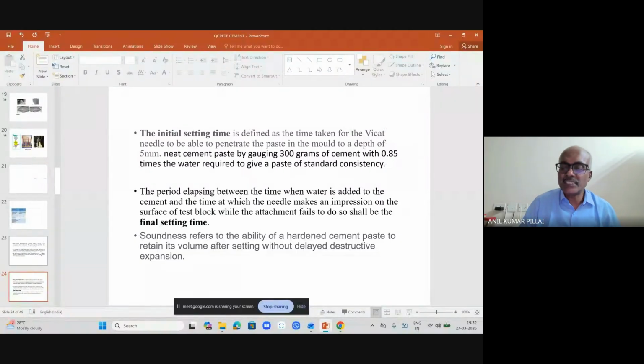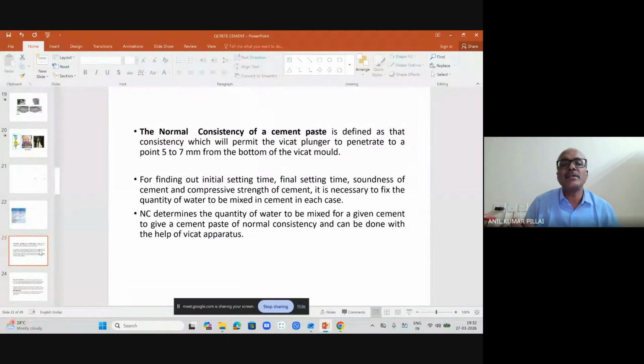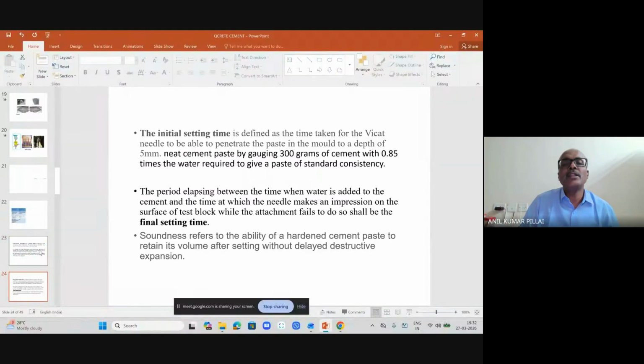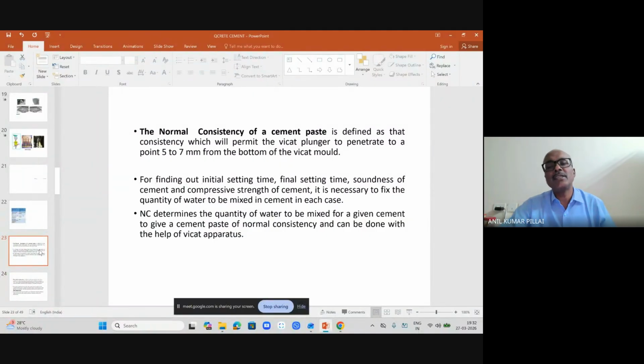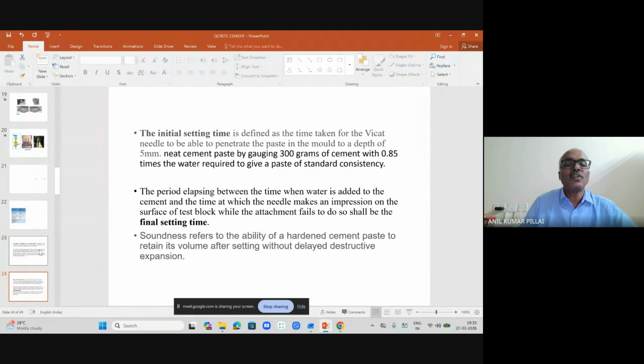So if your NC changes, if there is a mistake in measurement of NC, then your initial setting time value, final setting time value, your compressive strength of cement mortar can change. So it is very important that you measure the NC correctly. That is why in many project sites, when you are attempting testing of cement at the site, you need to be very careful as far as NC is concerned, because the moment there is an error in the measurement of normal consistency, you will find that the other parameters change.